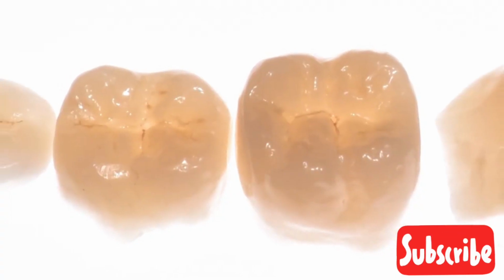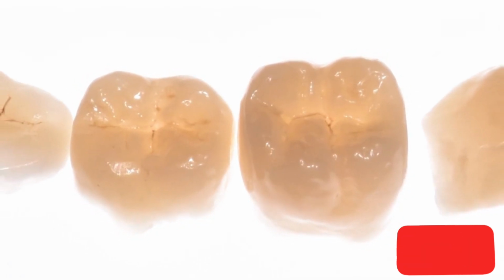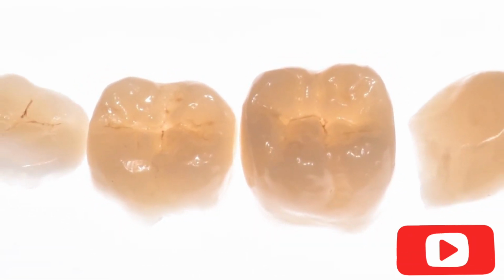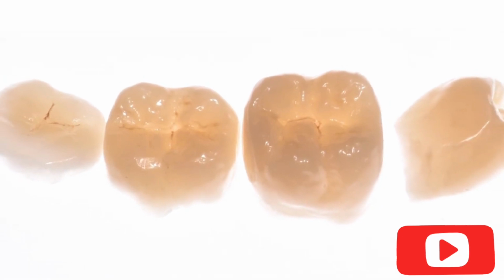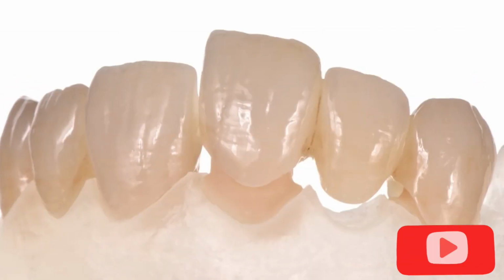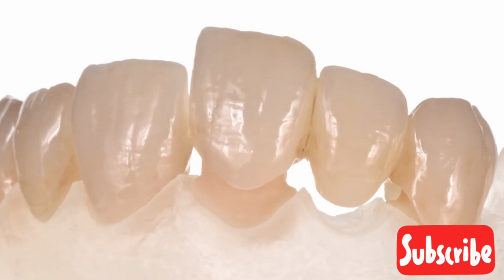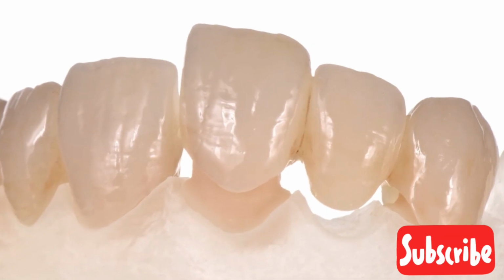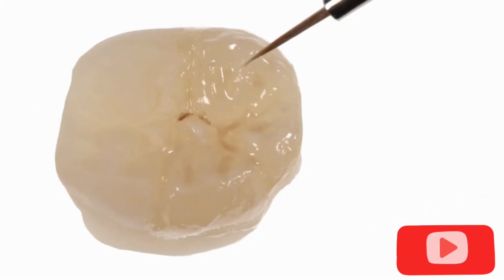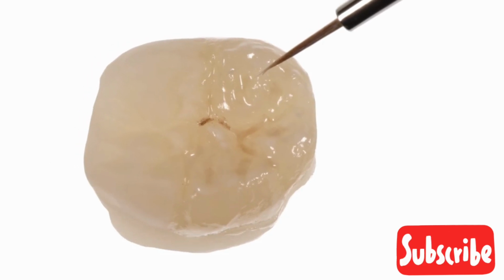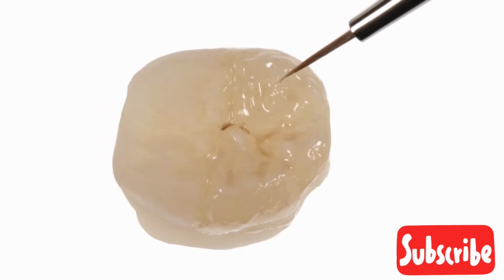The zirconia-reinforced high-strength lithium silicate ceramic Celtra Press was the material of choice for the new monolithic crowns. In addition to a stability of more than 500 megapascal, this high-strength glass ceramic offers high translucency and a pronounced chameleon effect, resulting in aesthetically appealing restorations with the staining technique.